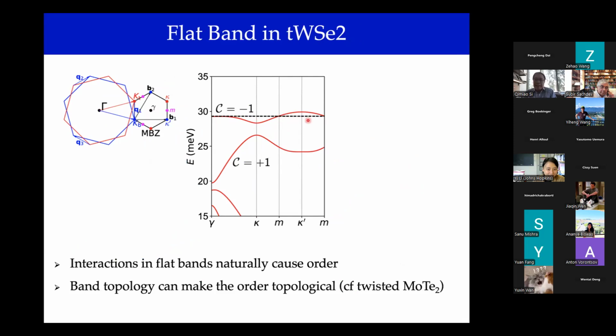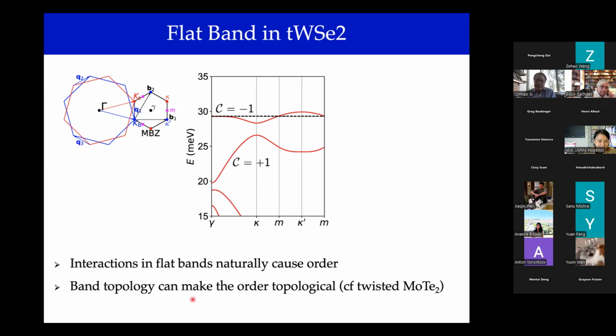And so if one has a flat band, certainly at the model level, flat bands were historically introduced to have enhanced density of states to create electronic orders such as itinerant ferromagnetism and other possible electronic orders. And in cousin materials like twisted MoTe2, this kind of electronic order is in fact realized. There's ferromagnetic order, there's evidence for fractional Chern insulators. And so interactions in flat bands, if we want to look at the big picture view, it's very natural to cause order, and the band topology can make the order topological. So these are systems that have been a very good setting to study these topological, say, fractional Chern-like systems.